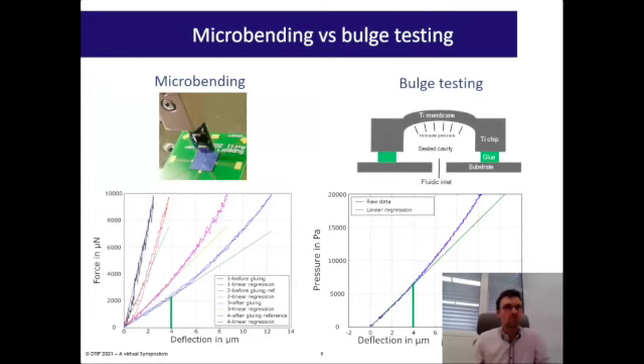The microbending results were also compared qualitatively to previously obtained bulge test results for the same tip. What can be seen is that there is a good agreement between the previous results and the new ones. Indeed, in both cases, a non-linearity becomes significant at around 4 microns of deflection, which shows a good consistency of the experiments.